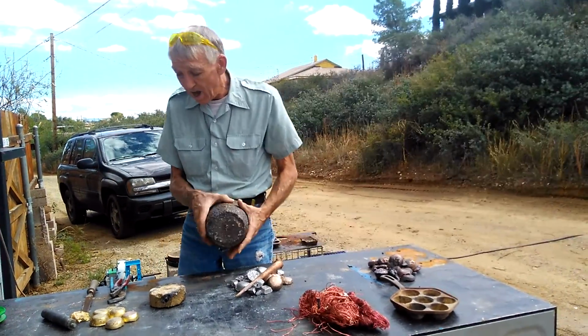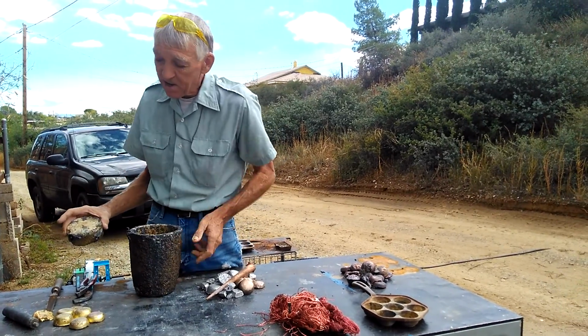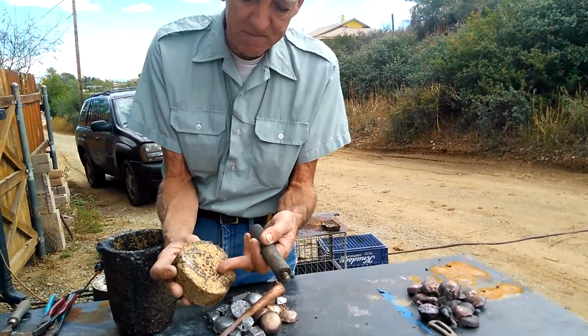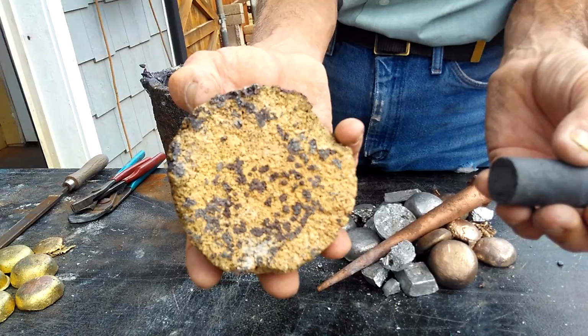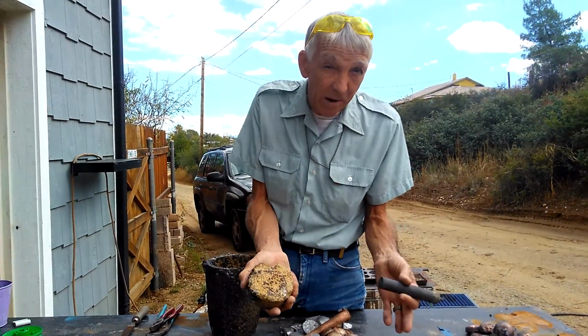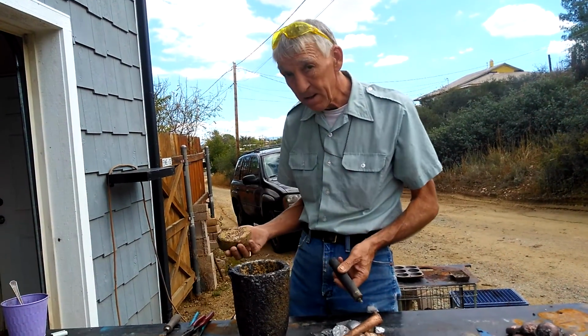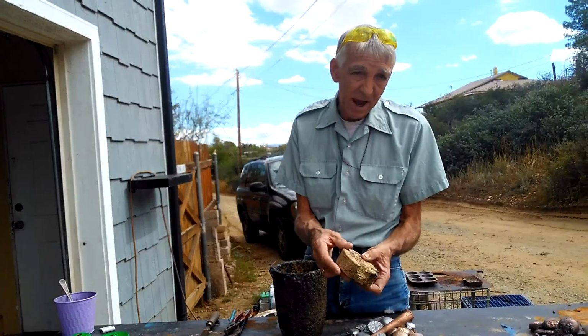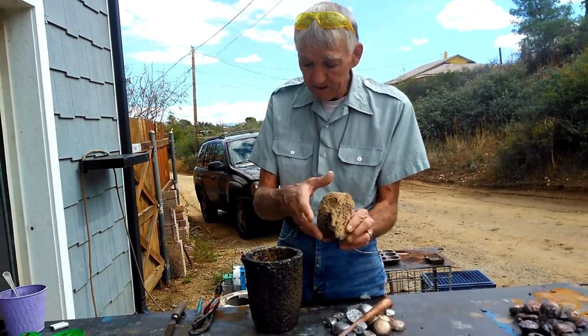But first of all, before we do that, on the second pour, I told you about smearing a carbon rod on your plinth, and you can see that it almost looks metallized or something. I don't know if that does any good, because on the third pour, the plinth did stick to the crucible. And I just left it on there until I was done with this 21 pounds of copper. And then on the last pour, I rubbed it off. And it's still in good shape after 36 pours. After 30, we showed you the chunks out of it.